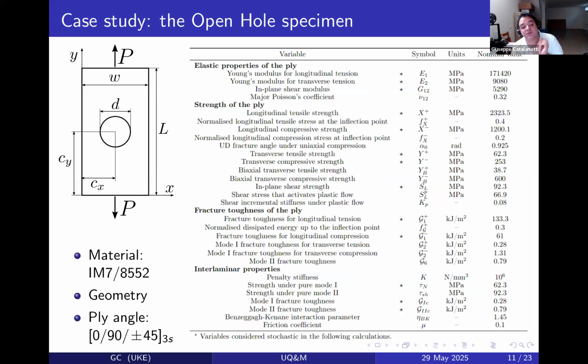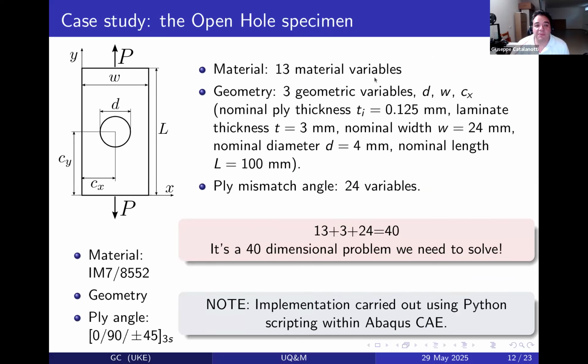This is 0/90/±45 3 times symmetric. That means 24 plies, and therefore we can also assume to have 24 misalignment angles. So if I go here, I could say that apart from the 13 material parameters, I might have also 3 geometric variables that can be assumed to be stochastic. Therefore, the diameter, the width, the position of the hole. Some do not play a role, therefore are assumed to be deterministic. And of course, the ply mismatch angle. Since we have 24 plies, we'll have 24 variables. So if we take into account all these variables, we have 40 stochastic variables. So it's a 40-dimensional problem that we need to solve.